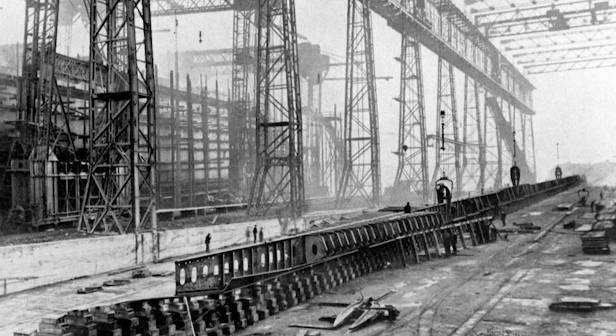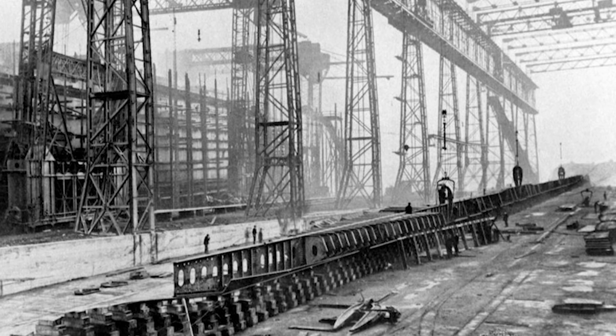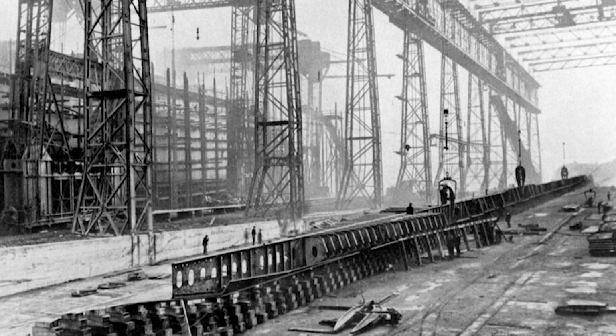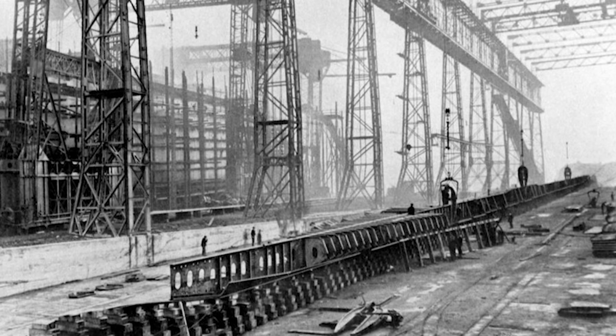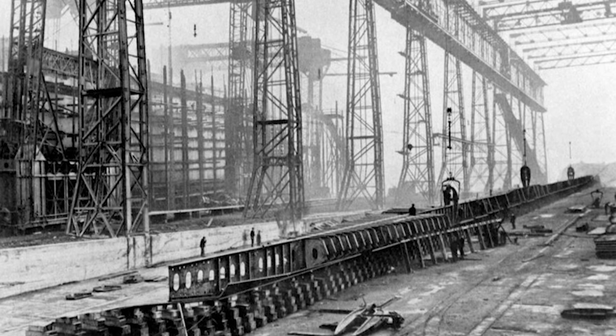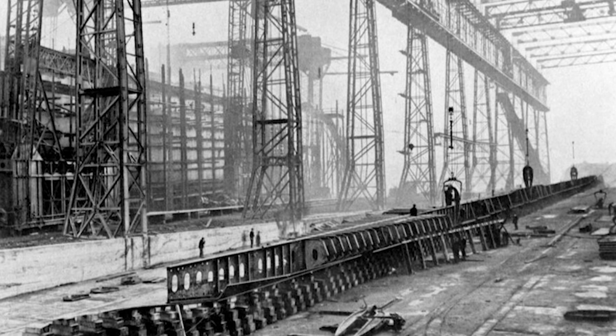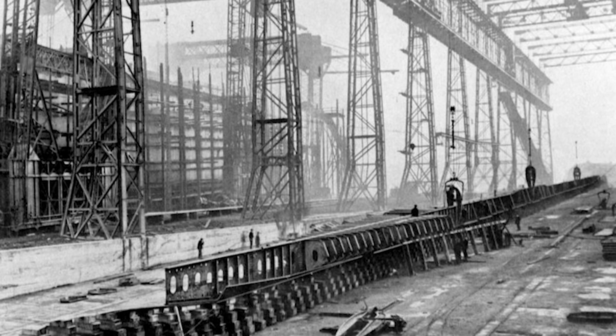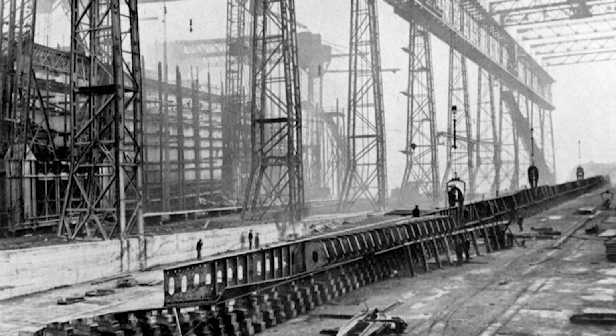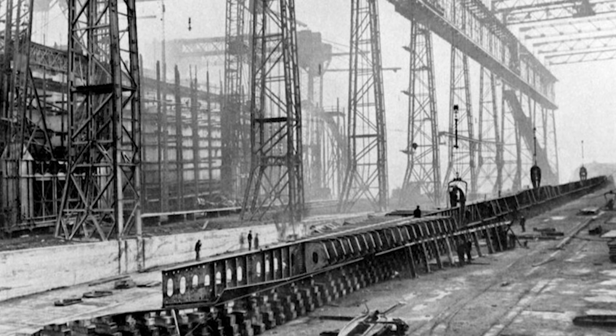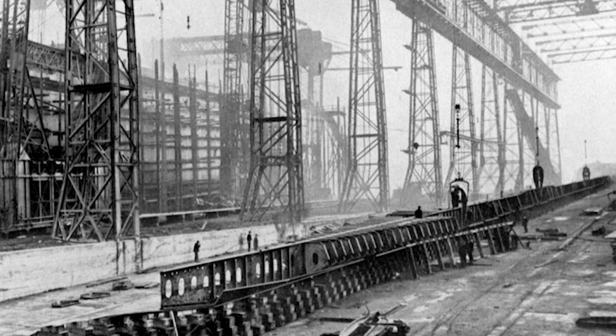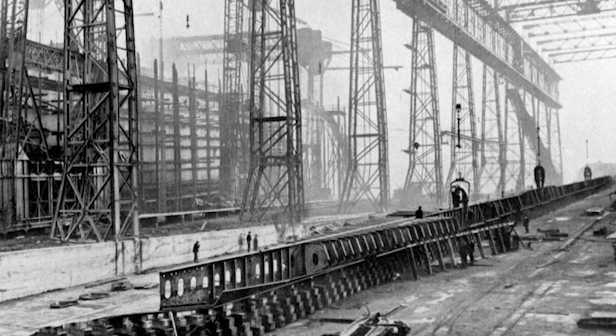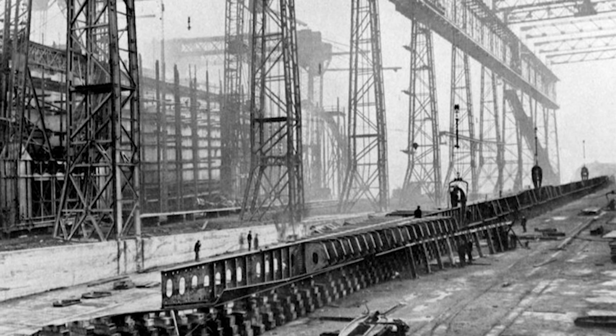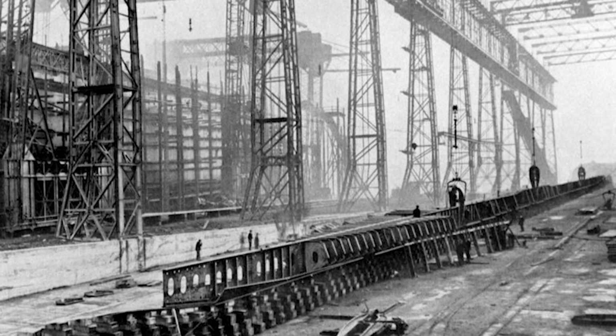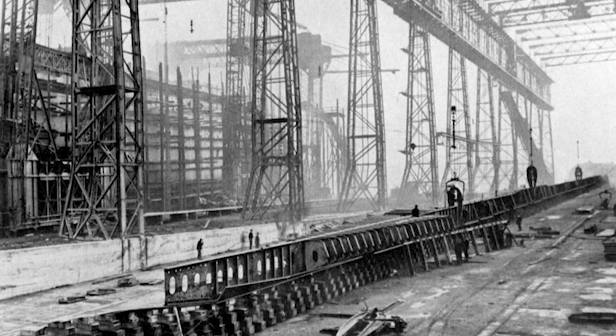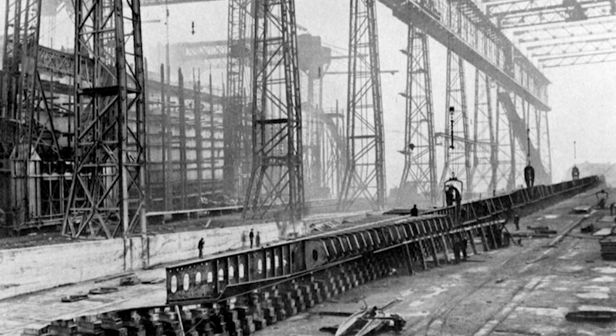Steel containing high sulfur content, a characteristic of wartime materials produced under emergency conditions, exhibited transition temperatures as high as 50 degrees Fahrenheit. Below this critical threshold, the atomic structure of steel changed its fundamental response to stress, transforming from a material that could absorb energy through plastic deformation into one that transmitted stress waves at the speed of sound through crystalline fracture patterns. Most significantly, Tipper's analysis revealed why welded construction amplified the brittleness problem, while riveted structures remained